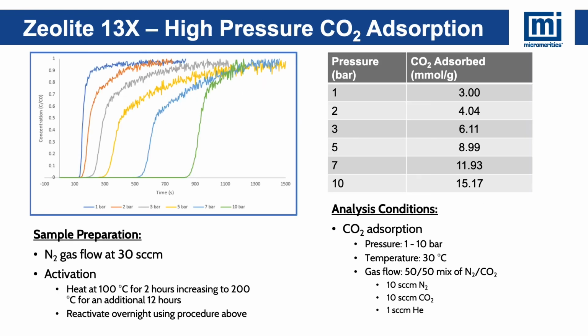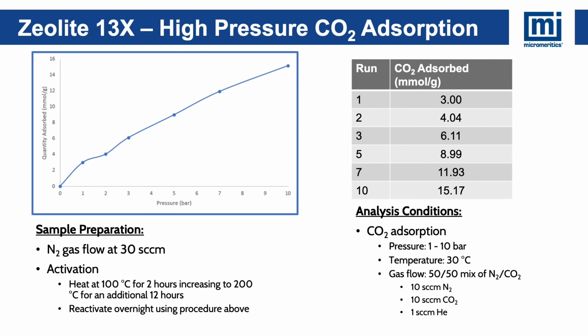So shown here are the breakthrough curves on the left, as well as the quantities adsorbed on the right. We see a constantly increasing breakthrough time as we go to higher and higher pressures, which is what we would expect since we're adsorbing more and more CO2. We see a first pass capacity of around 3 millimoles per gram, and then by the time we reach 10 bar, we're at about 15 millimoles per gram adsorbed. Then, since we're looking at equilibrium quantity adsorbed for our final adsorption capacity, we can actually translate this to an isotherm, which is shown here, where we can see the increase in our equilibrium CO2 adsorption as we increase our pressure.